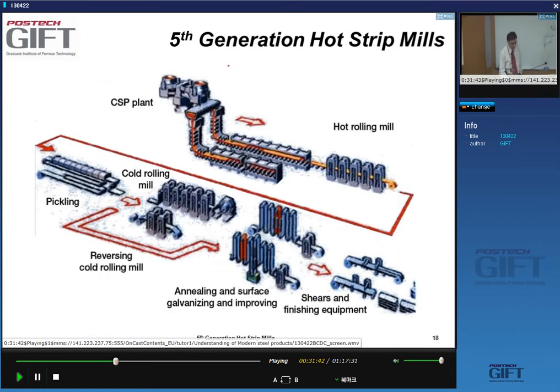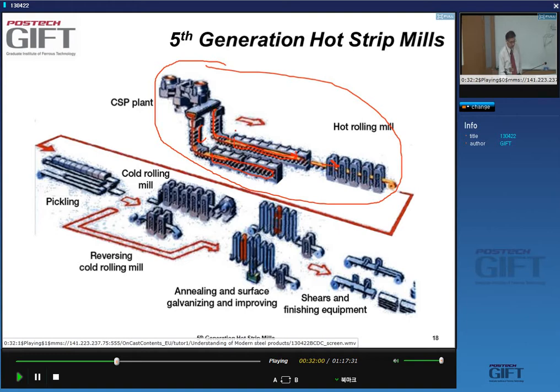Okay, so CSP plant shown here. You have two strands of material. You keep them in a tunnel furnace before you go to the finishing mill. And there are two because the casting speeds here are too low to feed whatever you cast directly and continuously into the finishing mill. After that, the coils you make, you can basically process them the way you process a conventional coil. So they can go straight to the market or then go to cold rolling plants, as we will see later.